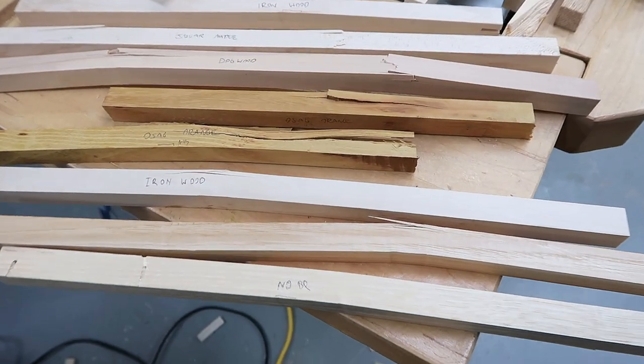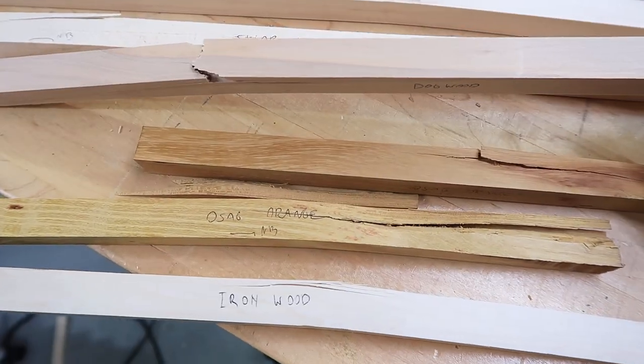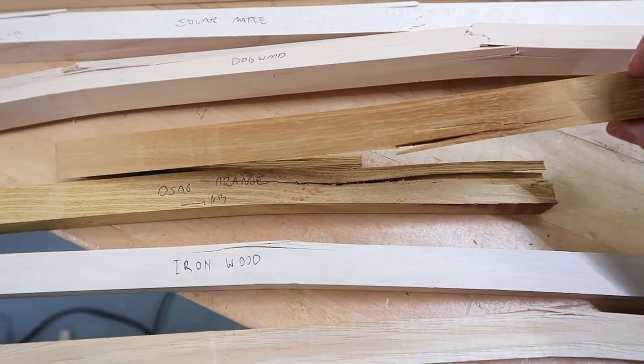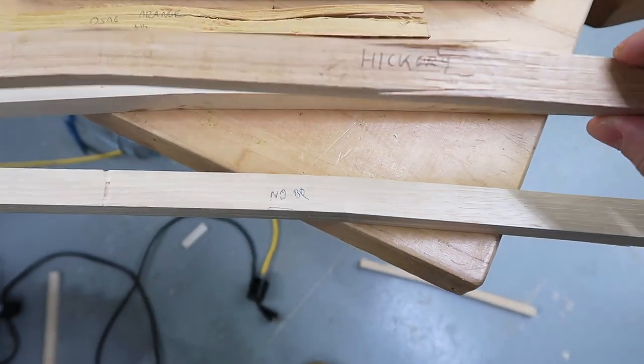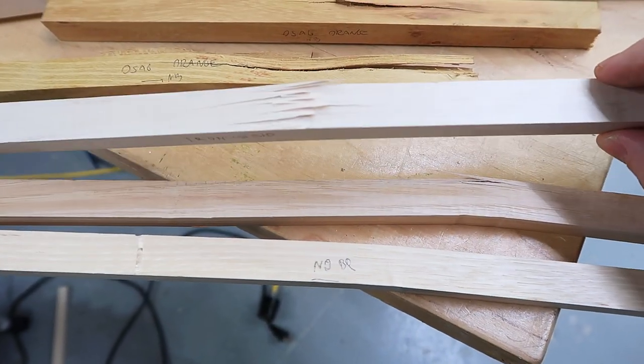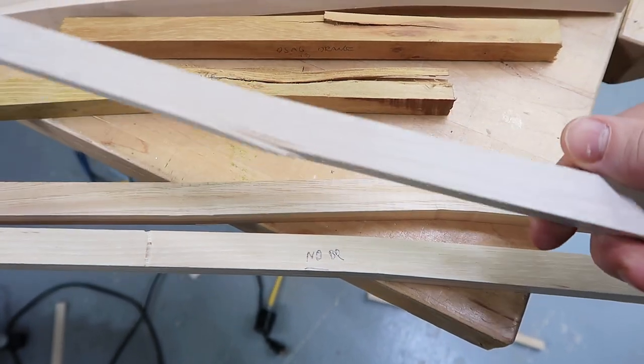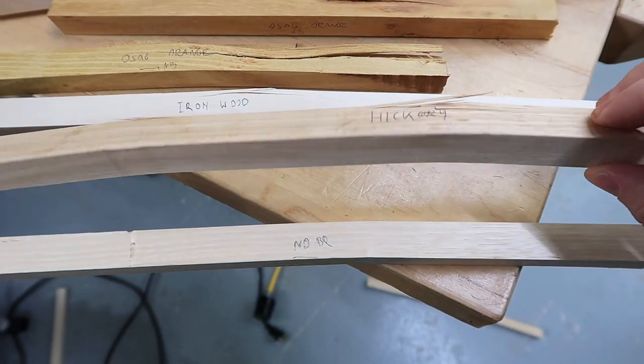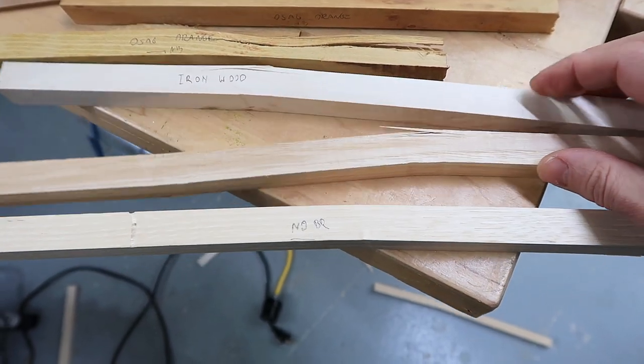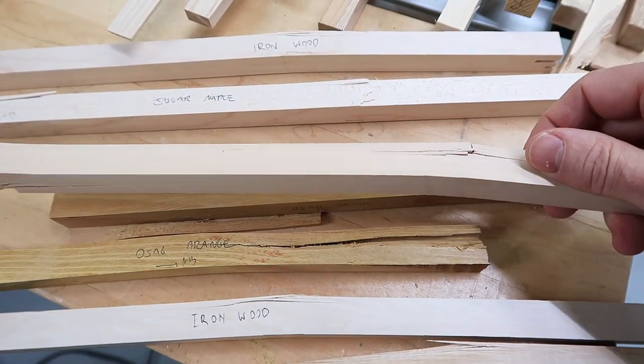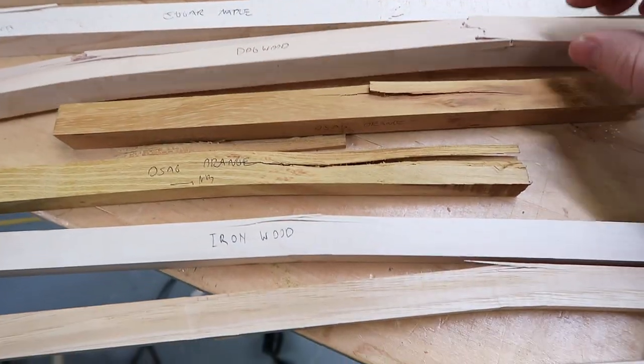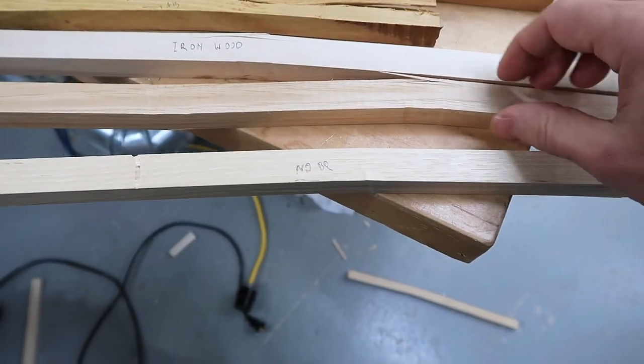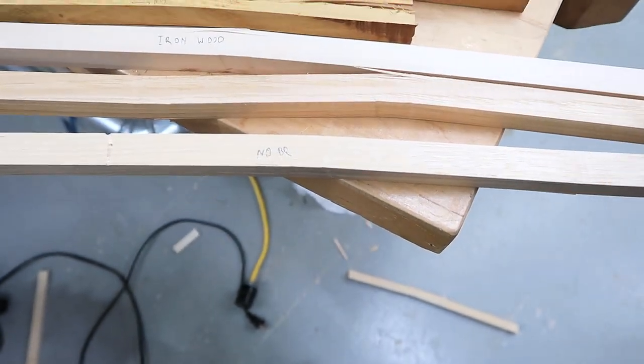Although looking at how the samples broke, the dogwood, the way it broke, it kind of broke with a bang, and so did the osage orange, whereas the hickory and the ironwood started to splinter off a bit, which is to say they gave a bit of warning before they went, which is much more graceful for making a bow. You don't really want it to just go bang and snap in half like the dogwood or the osage orange would. So that makes the case for making a bow out of hickory. And I'm not planning on making any bows or anything of that sort, it's just out of curiosity.